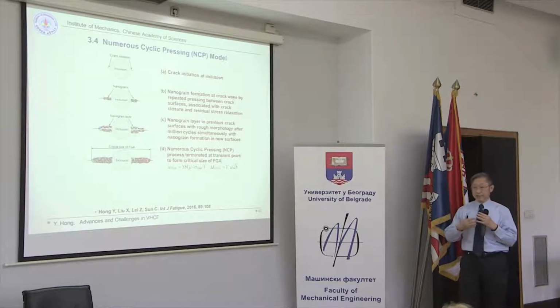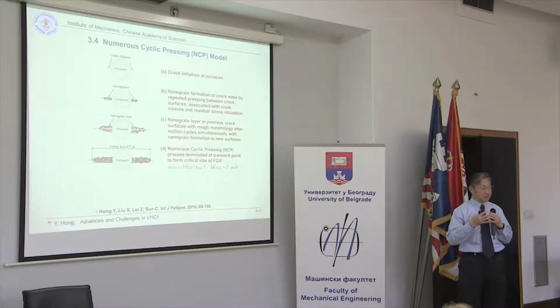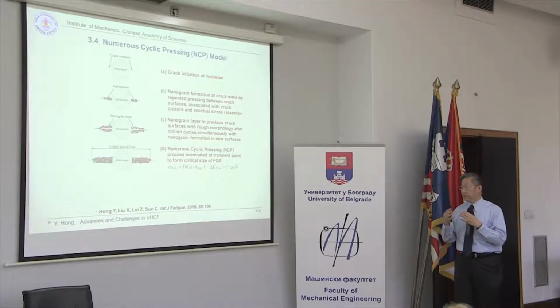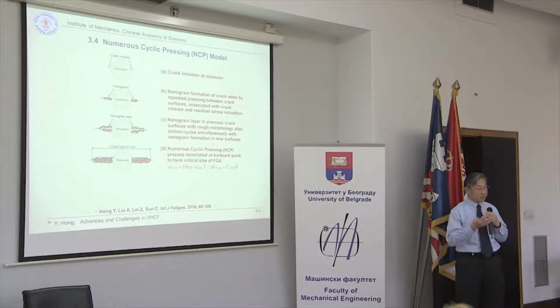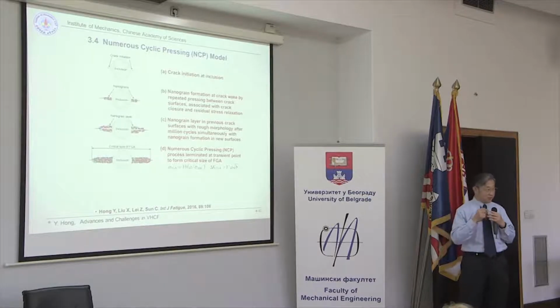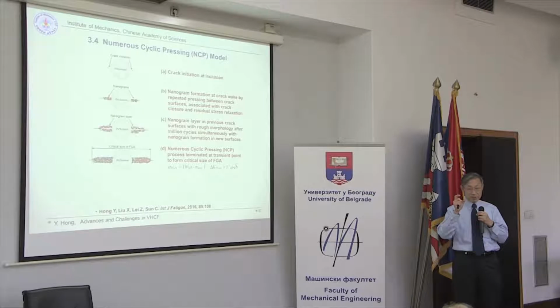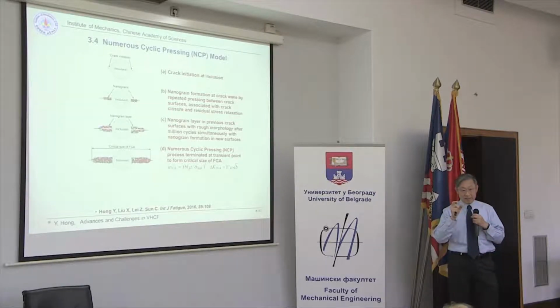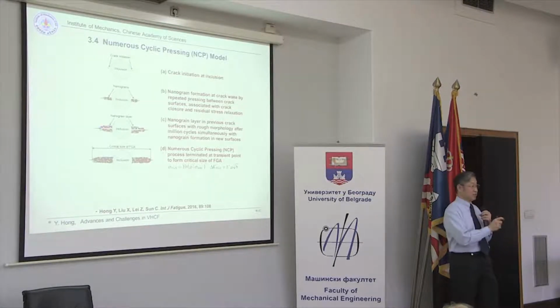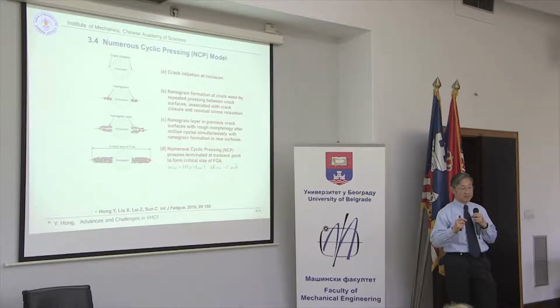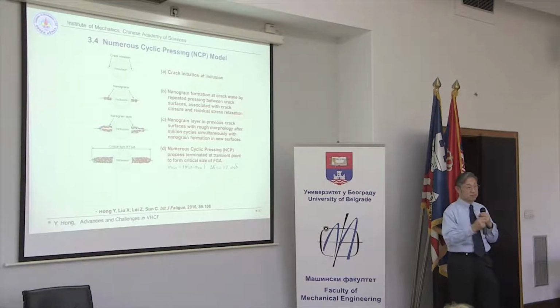And this process is possibly to produce refined microstructure. It is our basic consideration, or the main concept of our model. Or briefly speaking, our model emphasizes that this type of initiation characteristic region is formed after the crack initiation. But previous ones said it was before. Our model is after the crack initiation, and due to the mechanism of crack closure and residual stress relaxation.